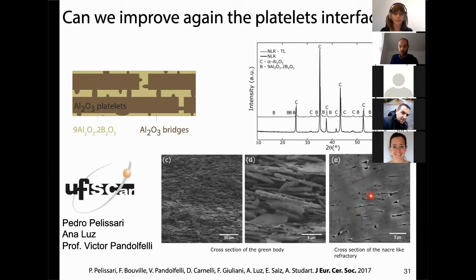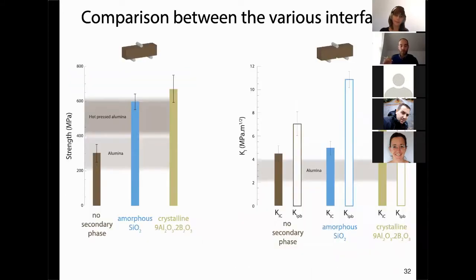You can see the process is the same. The microstructure is very similar again. And if we look at the mechanical properties now, from no interface to the glassy interface to the crystalline interface, what we see in terms of strength first is that for no interface, we obtain very typical values for alumina, so conventional alumina.